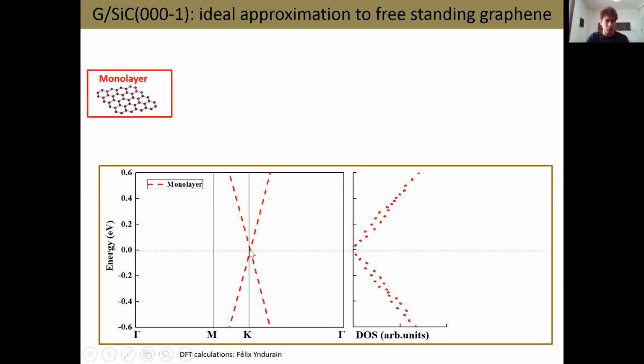That's the band dispersion for monolayer graphene. We have the Dirac cone here, okay? And this is the density of states that you get for a single layer graphene, okay? That's DFT calculations.